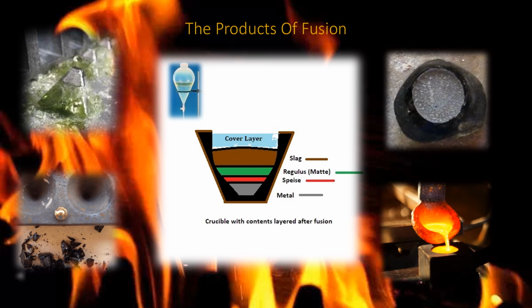The next layer, which should be the only layer present, is the slag. Slag is the fusible compound of the metallic oxides, silica, and other acidic constituents. It will be a homogenized alloy of silicates, borates from the fluxes added to the charge, as well as the metallic oxides from the ore material. The slag can be considered as a solid solution, commonly referred to as eutectic solutions. At times they can be a mix of chemical compounds. Besides being homogeneous, a good slag must be free of any undissolved ore material. It should be glassy and brittle, more or less, and as a molten solution it should resemble a very thin fluid, free from any lead shot.